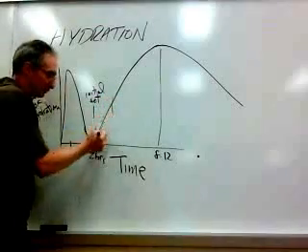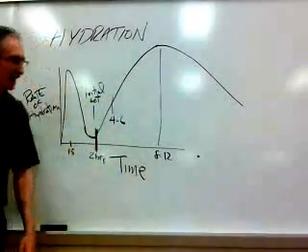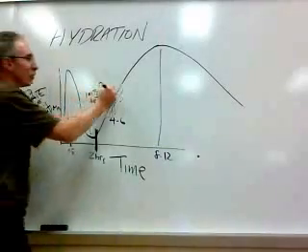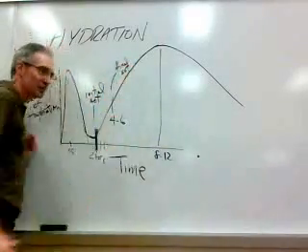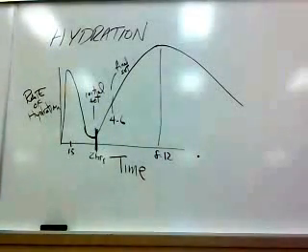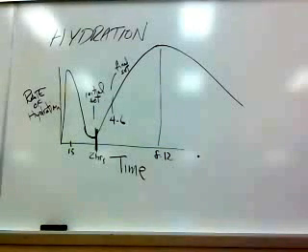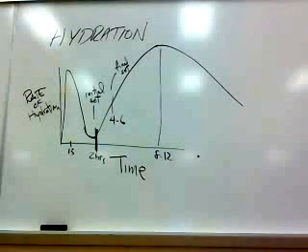After about maybe 4 hours, maybe 6 hours, something like that, that's probably what they're going to call the final set. At this point in time, the concrete can support some loads. Not like you're going to drive a truck across it or anything, but you can walk on it. All right? Maybe you don't want to walk on it, but there's a point in time where it starts to be able to support loads.